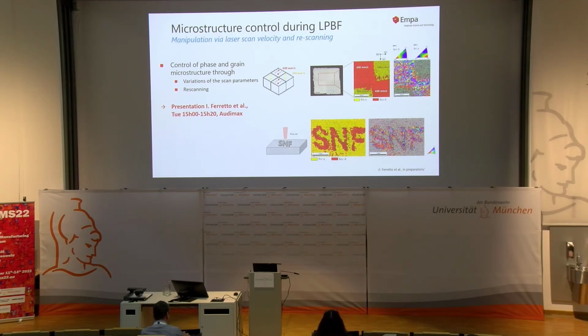Because I already advertised that. So we could find out that we can control phase and grain microstructure through variation of the process parameters, but also during rescanning. So we can, on demand, make BCC areas or FCC areas, or by rescanning we can start writing into our material and play with the two phases. We can also later on heat treat that and create different grain microstructures. And I just want to advertise that.